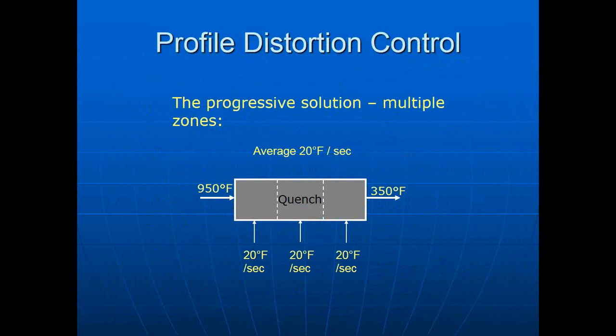The solution is progressive quenching. This involves using a quench with multiple zones and adjusting the performance of each zone. If the specification is 20 degrees per second, in theory, what we'd like to do is have about 20 degrees per second in zone 1. We'd like to have about 20 degrees per second in zone 2, and we'd like to have about 20 degrees per second in zone 3.